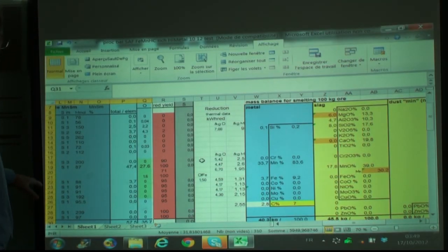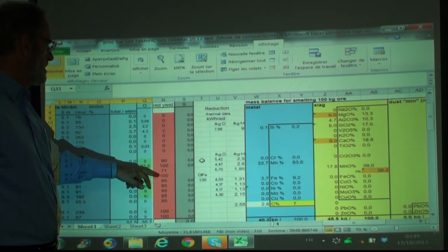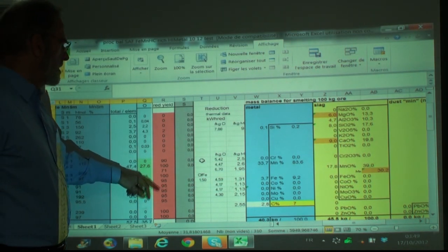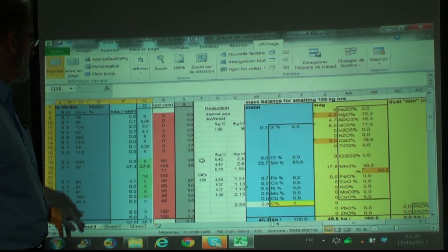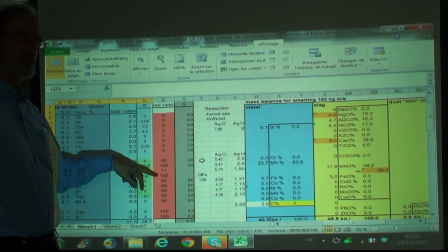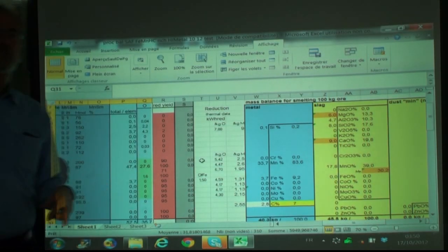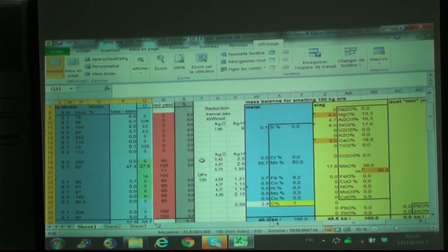And you see afterwards in the case of Fe, it's a bit similar to manganese because you have Fe2O3, which is of course fully reduced, and this is FeO, which is nearly fully reduced but not fully. But as for MnO2, the higher oxide disappears completely.